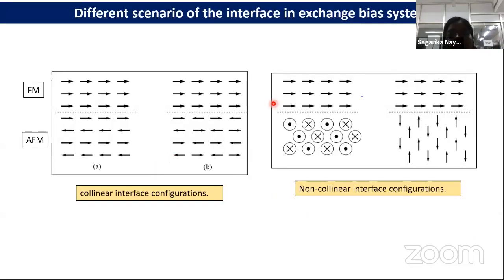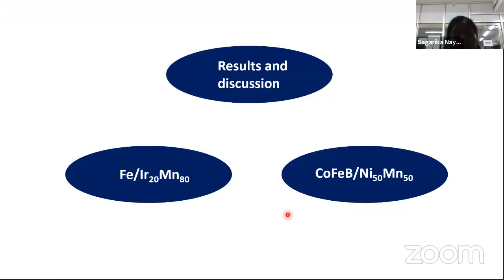Now these are different scenarios of the interface of an exchange bias system. This is the collinear interface configuration, where the interface is fully uncompensated, while in B it is fully compensated, and the interface can also be transverse to the direction of the ferromagnetic moments. Now I'll move to my results and discussion section. I will basically describe the study of the interface of the ferromagnetic and antiferromagnetic system, and also the role of the bulk of the antiferromagnet on these magnetic measurements.